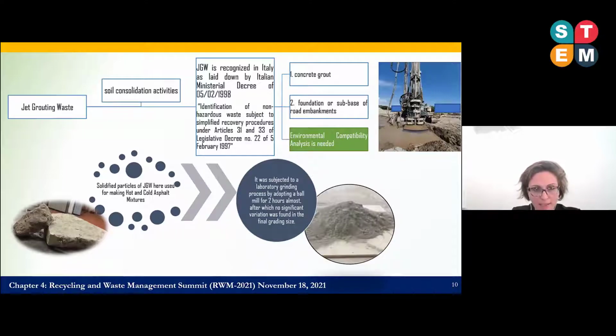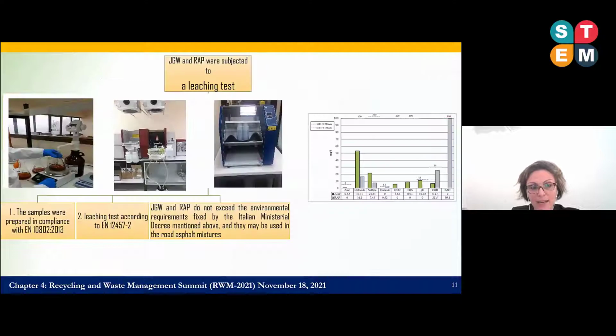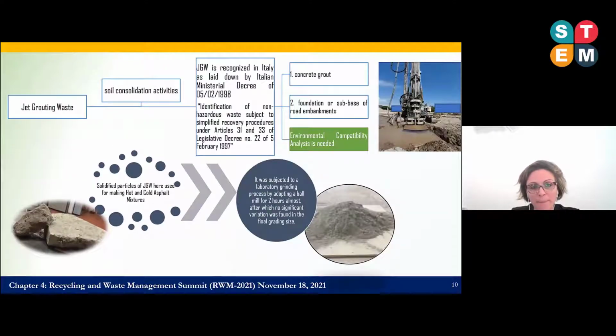The jet grouting waste used here derived from soil consolidation activities. In Italy, the use of jet grouting waste is recognized, but just for concrete grout and for foundation or sub-base of road embankments, after being subjected to environmental compatibility analysis. On the bottom left side, you can see the solidified particles of jet grouting waste that we have used. And on the bottom right side, the result of the grinding process, because the material was subjected to a laboratory grinding process by adopting a ball mill for almost 2 hours, after which no significant variation was observed in the final grading.